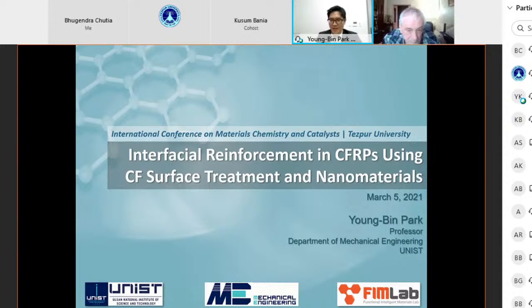So I've been thinking how we can deviate from this method and try to maximize the use of the nanomaterials' properties and let that be reflected in the overall property of the composite. And one way is by somehow concentrating the nanomaterials at the interface, because we know that the interface is the weakest link in a composite, and that determines the overall properties of the composite. So if you look at this schematic, the gray circular area is what we call the interface. And within the interface, if we could reinforce the interface with these high-strength nanomaterials, then we may expect that the overall composite property could be enhanced.